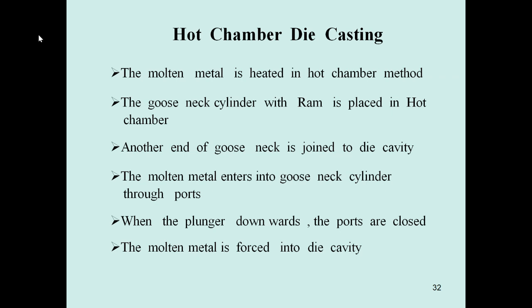The force is applied at a pressure of 14 megapascals. The molten metal is forced into the die cavity at a pressure of 14 megapascals.